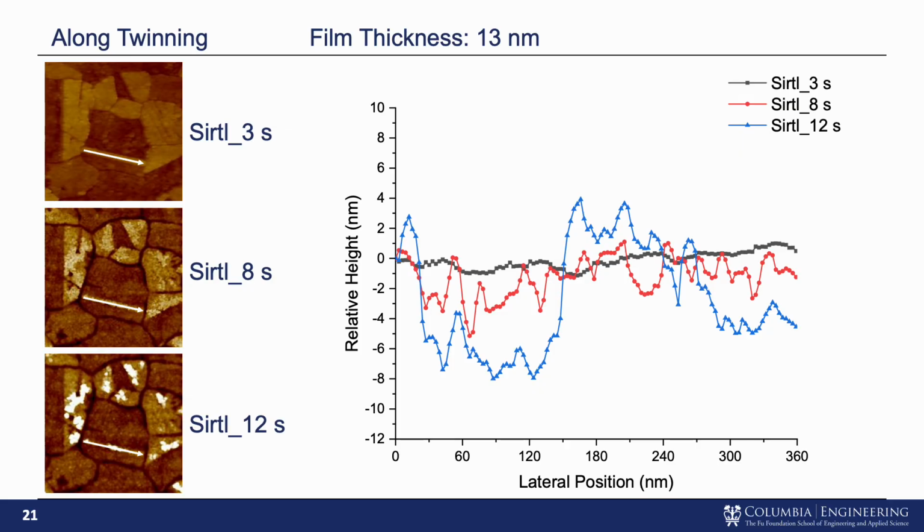Even though it looks like one line in the image, it can contain a high density of local defect sites, or subtle structural irregularity distributed along the twin plane. Under stir etching, these sites do not etch at exactly the same rate, so as etching proceeds, small differences in local reactivity accumulate over time, and the result is a more uneven topography along the same line.